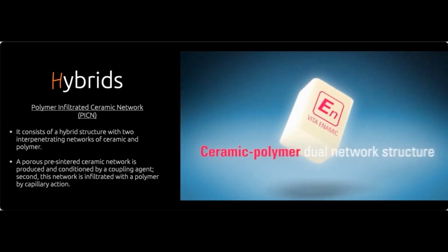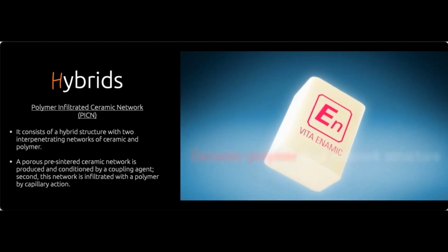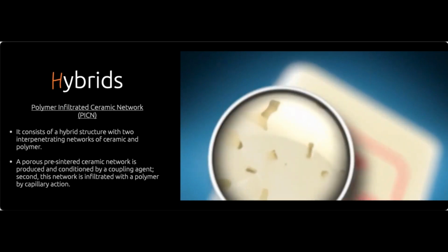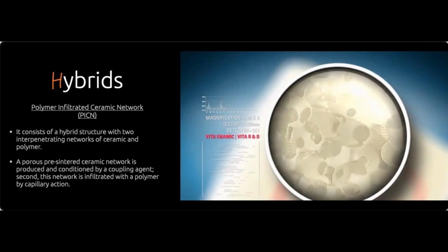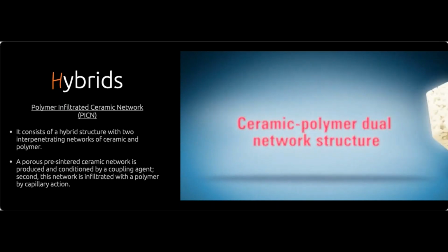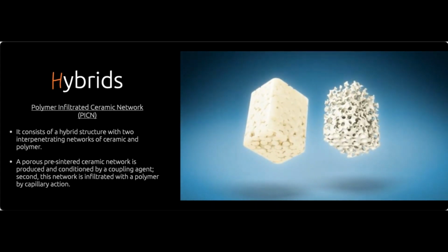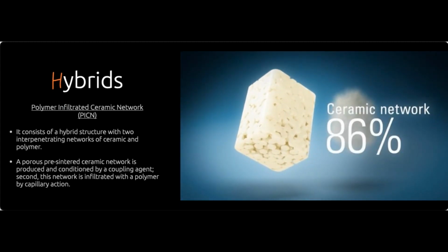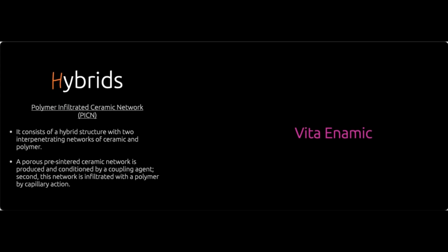And also, by putting resin into these pores, maybe we can stop crack propagation a little bit, because in ceramic, the crack goes from hole to hole, from hole to hole. And that's what they did. And then VITA acquired this technology, patented the technology, improved on the technology, and released to the market something that is called Enamic, right? So VITA Enamic is a glass ceramic. It's a piece of porcelain, very porous, that resin has been injected into it. So in a way, it's completely the opposite of any resin block, because resin blocks are a piece of composite with independent pieces of glass in it. But Enamic is a big piece of glass, one piece of glass, that is being infiltrated with liquid resin.